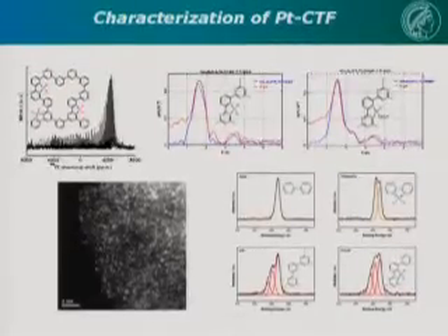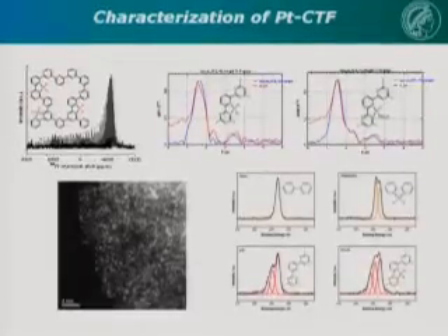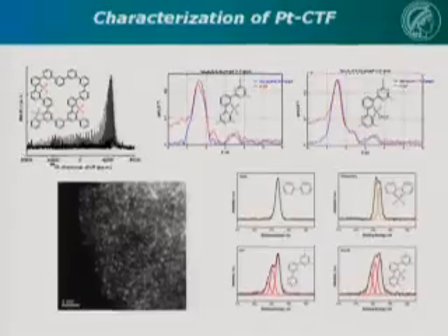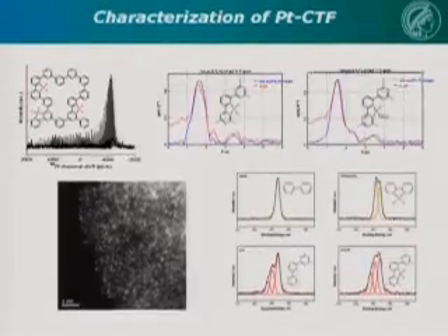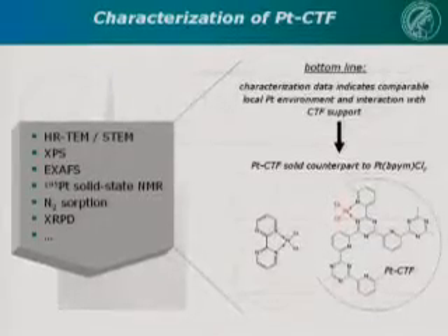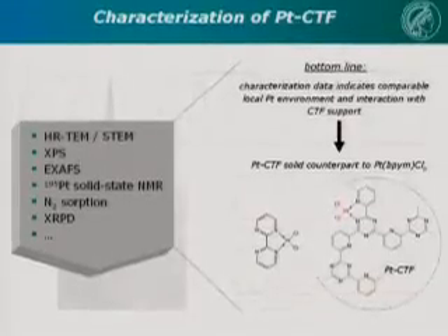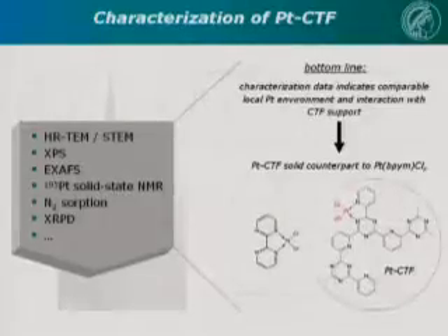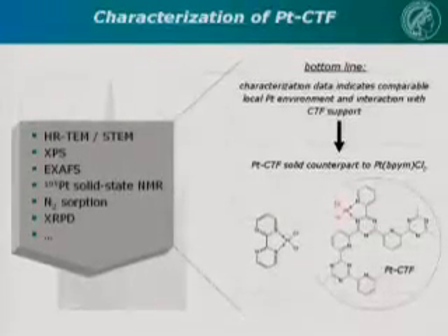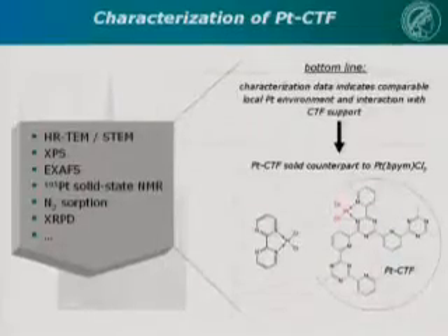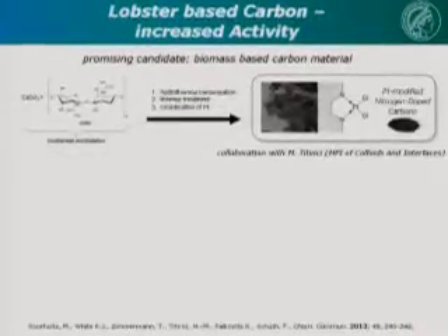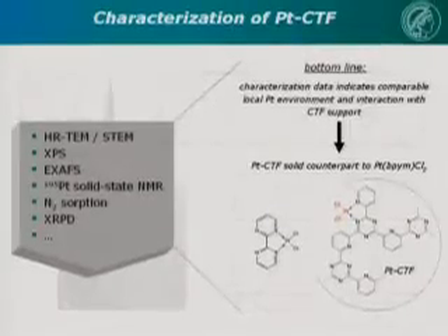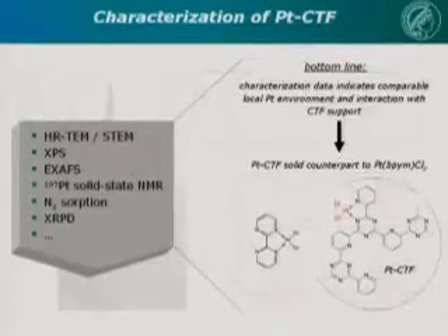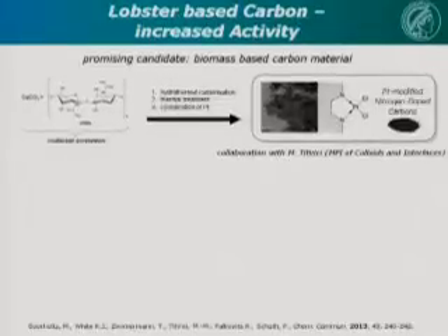Brad Chmelka was actually able to do platinum NMR on this solid, which is quite a feat in itself. We did XAFS and modeled the XAFS. We did XPS also on the nitrogen. Basically, what it comes down to is all the characterization data we have for the solid indicate that the coordination motif is basically identical to the molecular Periana catalyst, and this explains why it has basically the same type of reactivity. Unfortunately, activity was still roughly a factor 10 for this solid, even a little bit more, too low for meeting the benchmarks which the Catalytica people had set.